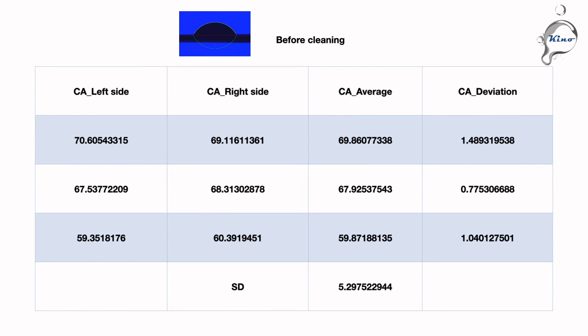If the surface tension value of milk is lower, such as 35 millinewtons per meter, the packaging box is likely to be wetted by milk and cannot be used. At the same time, the data above shows that the contact angle values of milk also present that the packaging box may be unclean before cleaning, so the standard deviation of contact angle at multiple measuring points exceeds 2 degrees.